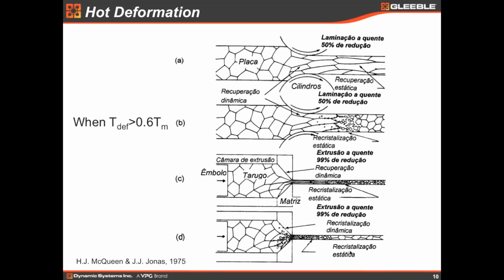When the deformation temperature is higher than 0.6 of the melting temperature, we consider that we're having hot deformation. I'm sorry for the Portuguese words. This is an original figure from a publication by McQueen and Jonas in 1975. I don't have a digital version, so I got that from my recrystallization book that is in Portuguese. But it's very simple, self-explanatory. In the first case we have rolling, a low or medium deformation, 50% reduction in this pass, again in this pass, and here you have extrusion, 99% area reduction.